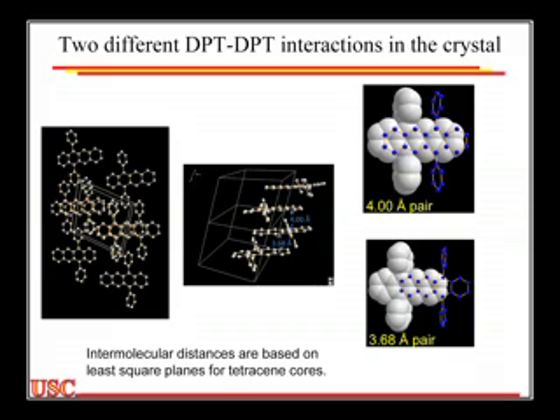And so what we think is happening in the film is that the prompt singlet fission that we see, the one that's sub-picosecond, is directly decaying at these dimer sites. And the one that's longer, 105 picoseconds, is the time it takes for the singlet exciton to diffuse and find one of these sites. And this is probably the site where the singlet fission occurs.